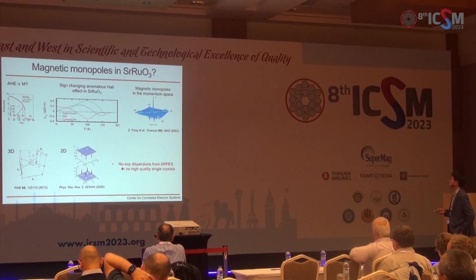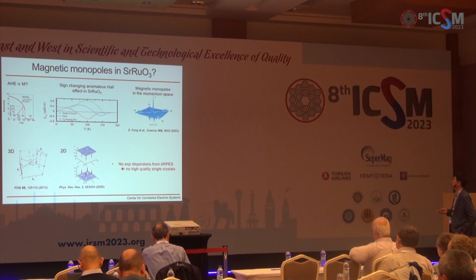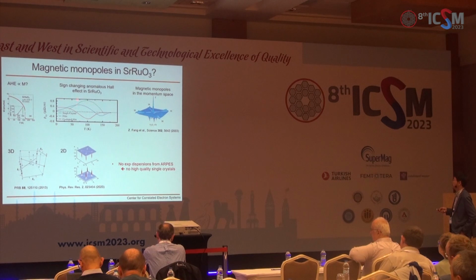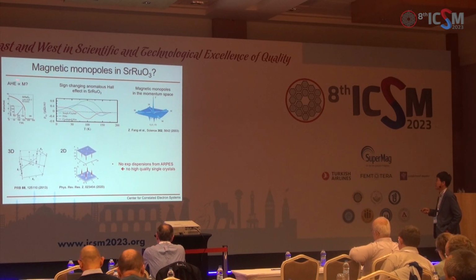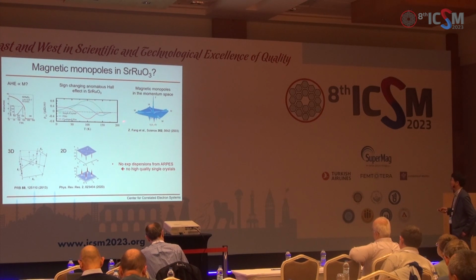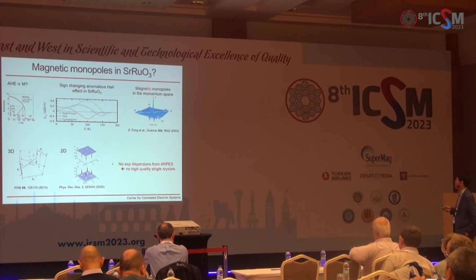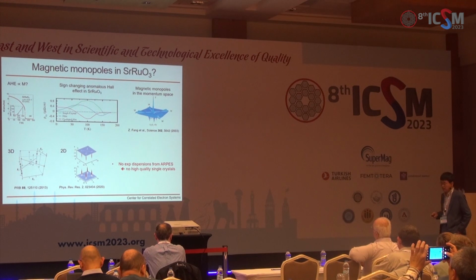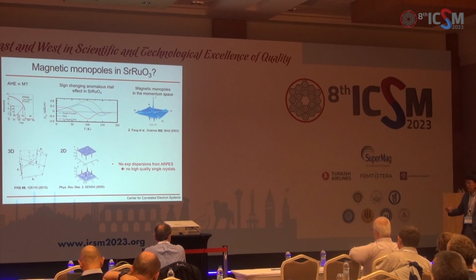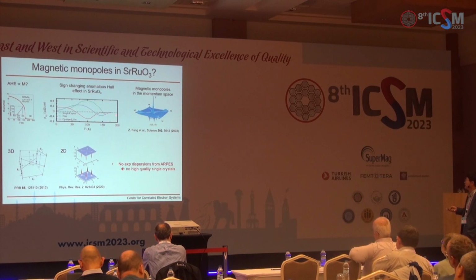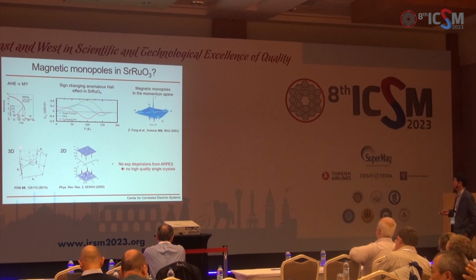However, it was reported that if you look at film and single crystal and some doped films, as a function of temperature, this anomalous Hall effect changes drastically, even changes sign from negative to positive. So why does it happen? Why is it not proportional to magnetization? The first suggestion came from the Nagaosa group about 20 years ago. They proposed that there's a magnetic monopole at the gamma point in momentum space. Then what can happen is that as you change temperature, this magnetic monopole moves up and down in energy, and they can cross the Fermi level. Then you can change the sign. So that was the first proposal, and that attracted a lot of attention. Soon after, some other sources came out.